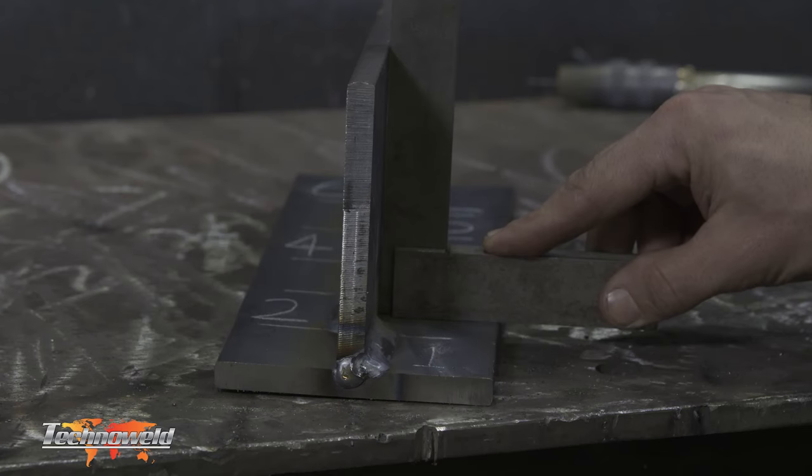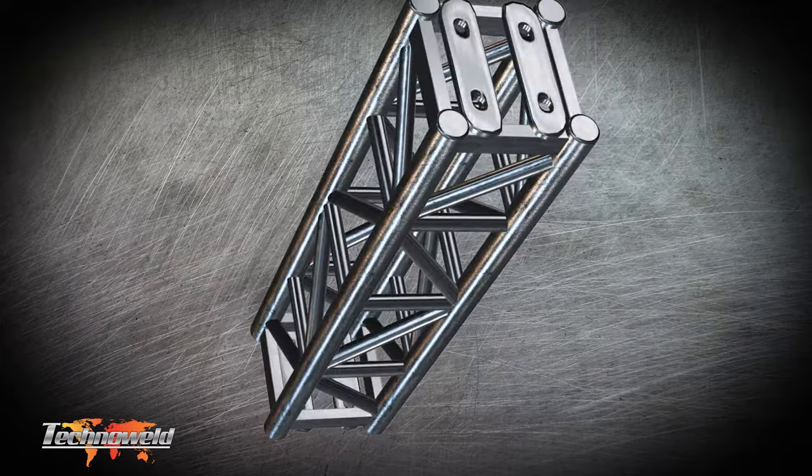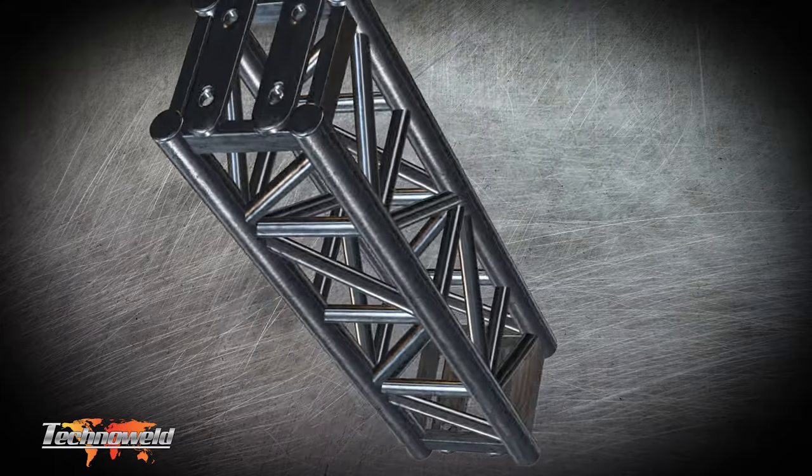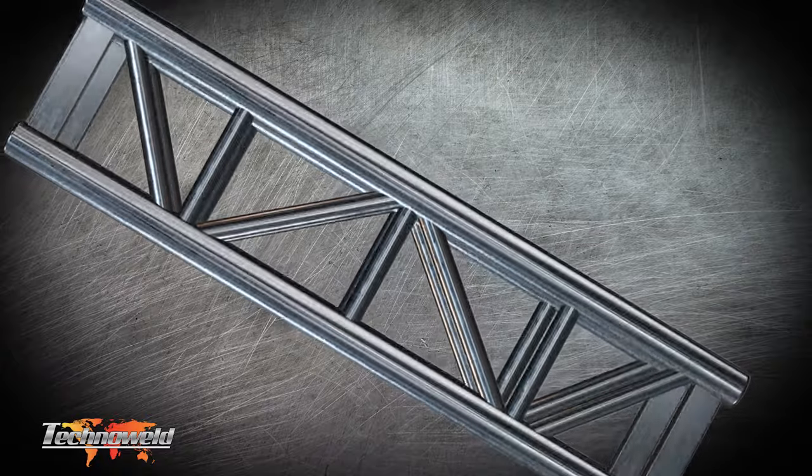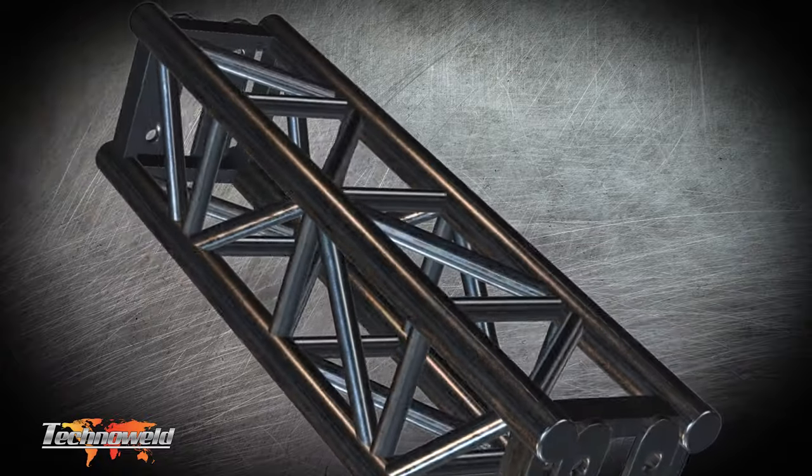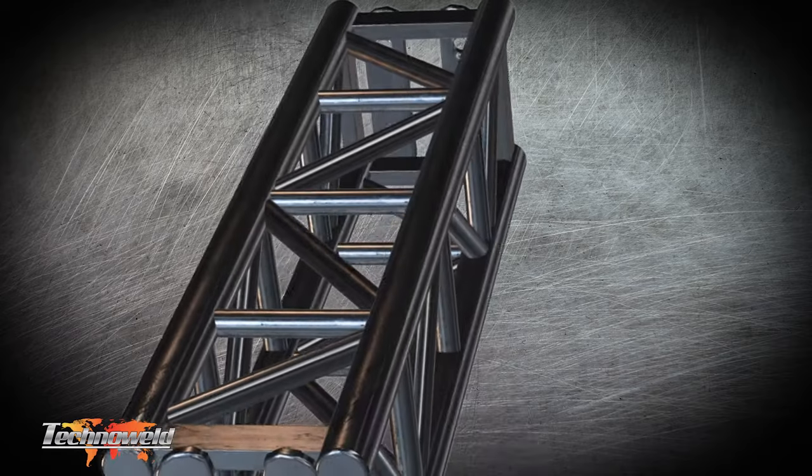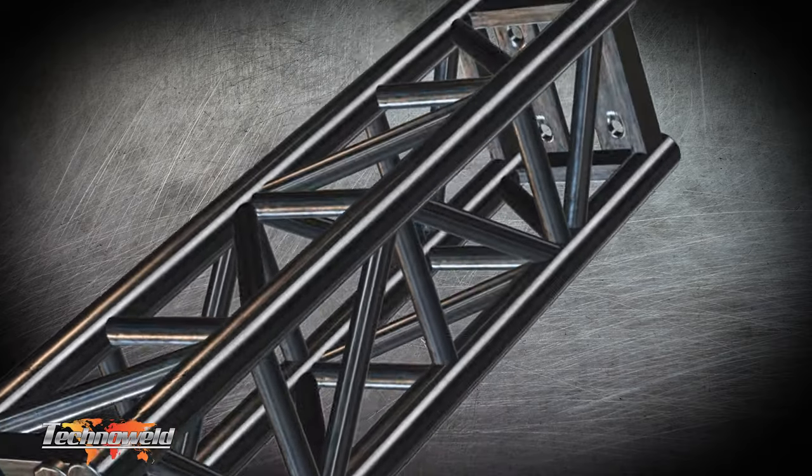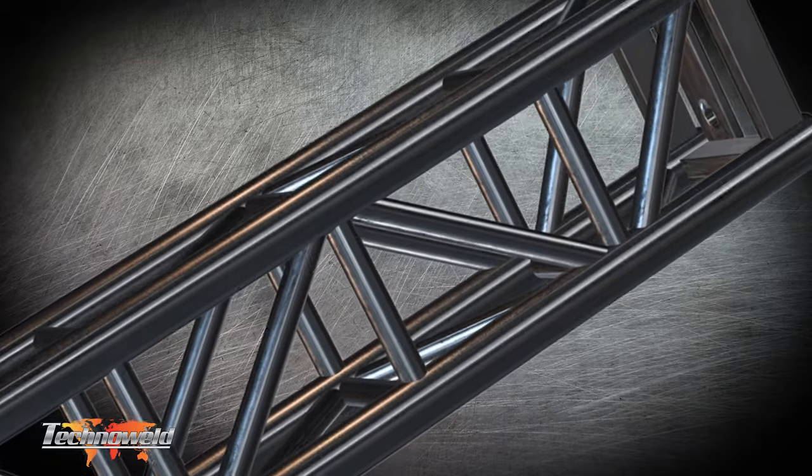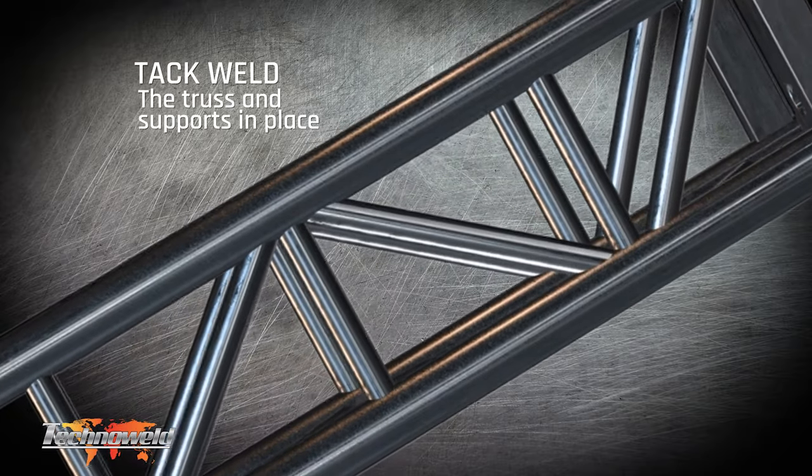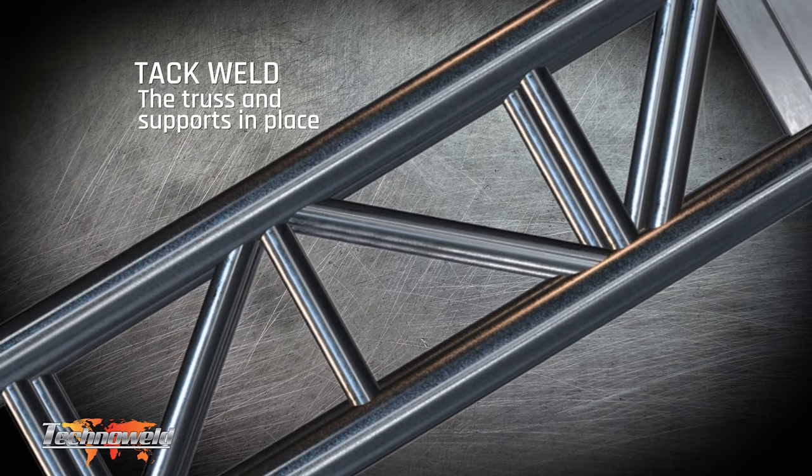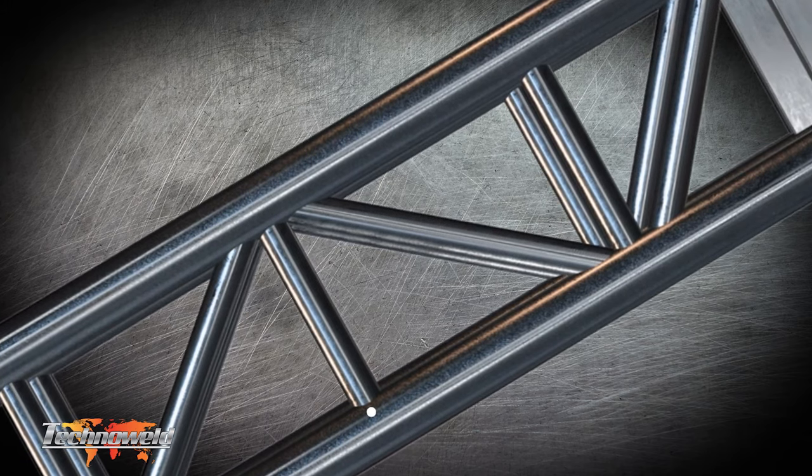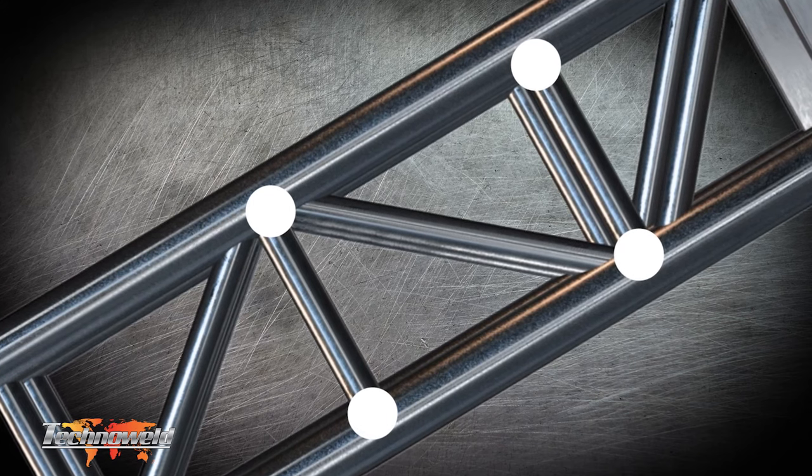When creating a complex structure, similarly to a crane boom or a truss, we need to use the correct welding sequence to stagger our welds to minimize distortion in the final product. These triangular supports are an example of how to correctly sequence a more complex job. Working our way up the truss, welding opposing corners as we go, one side and then the other, making sure that each force we create is counteracted by the next force. By planning out the welds and staggering them in this manner, we can control the amount of distortion.